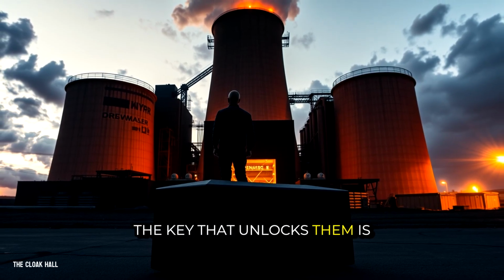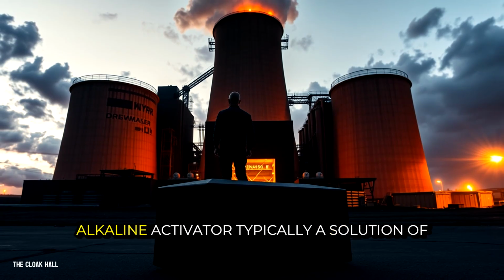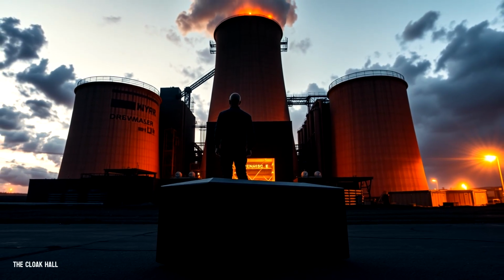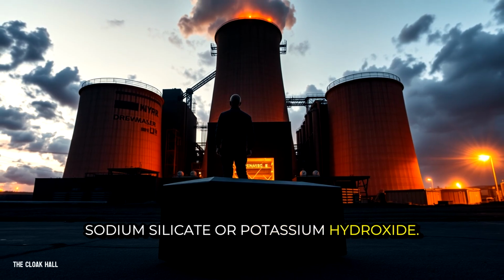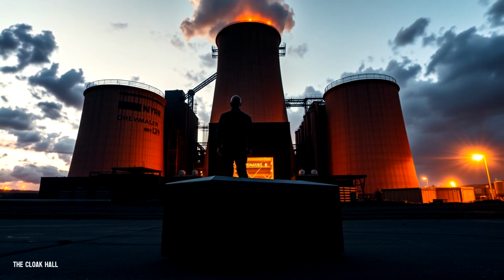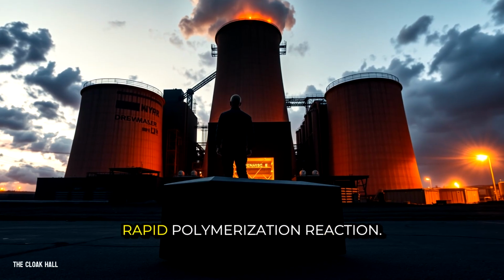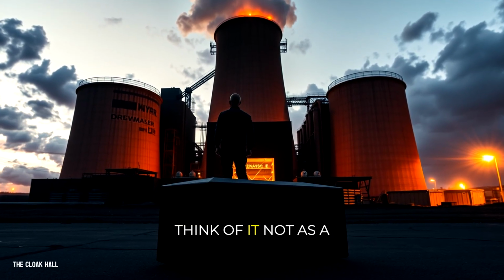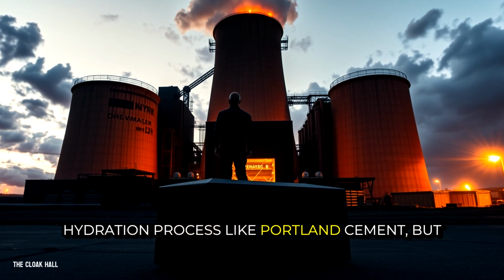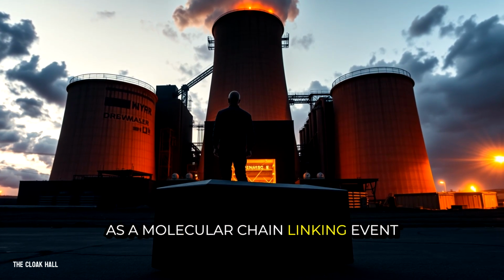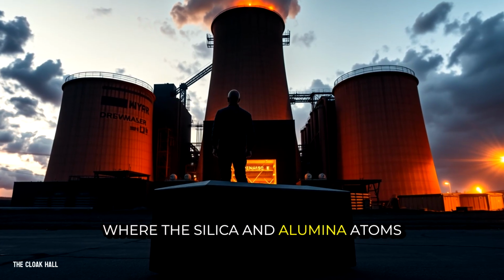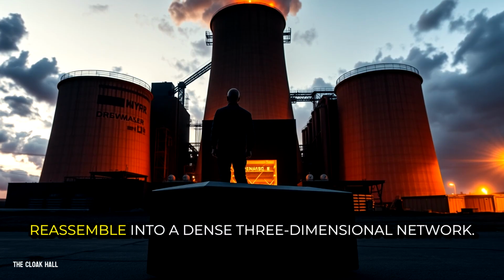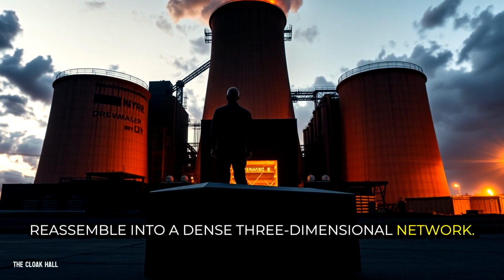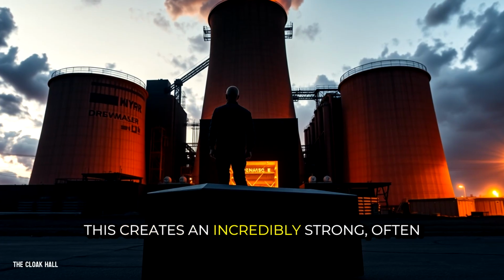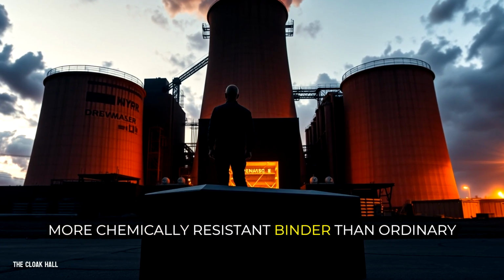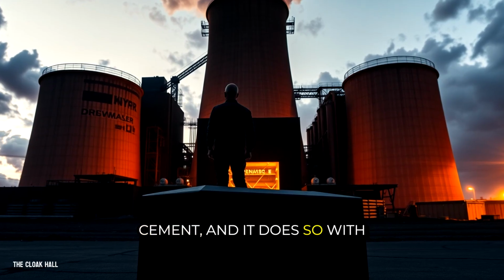The key that unlocks them is not slaked lime, but a strong alkaline activator, typically a solution of sodium silicate or potassium hydroxide. When this activator meets the fly ash or slag, it initiates a rapid polymerization reaction. Think of it not as a hydration process like Portland cement, but as a molecular chain linking event where the silica and alumina atoms in the waste materials dissolve and reassemble into a dense, three-dimensional network. This creates an incredibly strong, often more chemically resistant binder than ordinary cement, and it does so with a radically different environmental story.